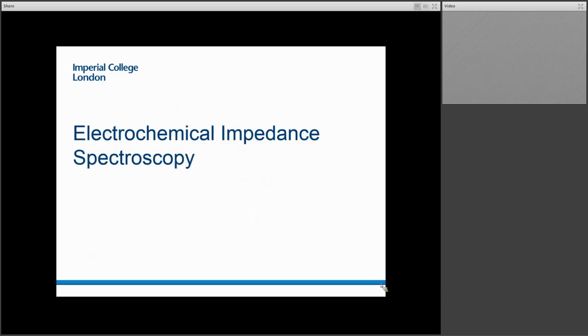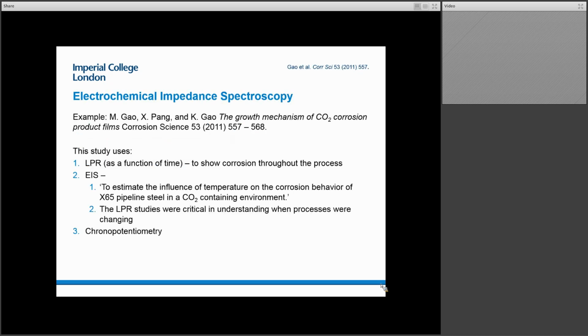But at the end of the day, if you go ahead and make that plot of corrosion rate, what you might find is that, in fact, it does give you something to hold on to. It gives you this number and you say, corrosion's getting better. But it doesn't give you the meaning that we just talked through by using an approach which was generated using essentially very, very similar data. So I would advocate that you use caution and certainly get more information if that's the approach you want to take. Okay, so I talked about that enough, and I do want to get to two other examples, and I know that the next example I have is going to be a little bit complicated for those of you who are not familiar with impedance spectroscopy.